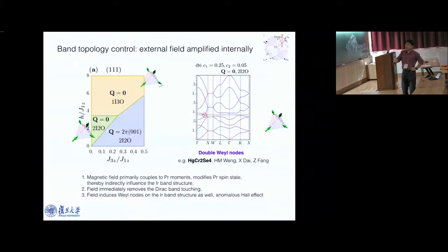And for different magnetic states of the local moment, the background provided by the local moment for the conducting electron is different, right? You have a different magnetic background for the conduction electron. For instance, if you take this state and look at the band structure of the conducting electron, it is reconstructed in a different way. Now there is no degeneracy at the gamma point anymore, but there is this emergent Weyl band touching, which is protected topologically here.